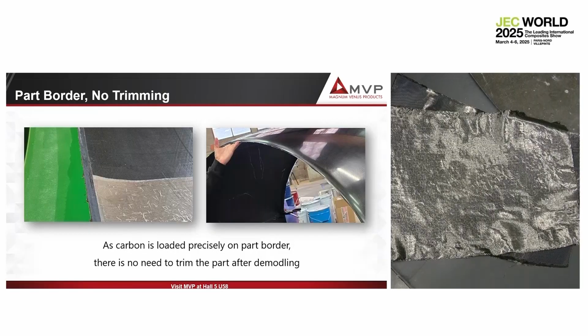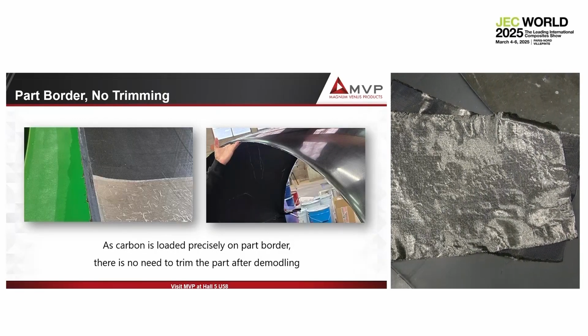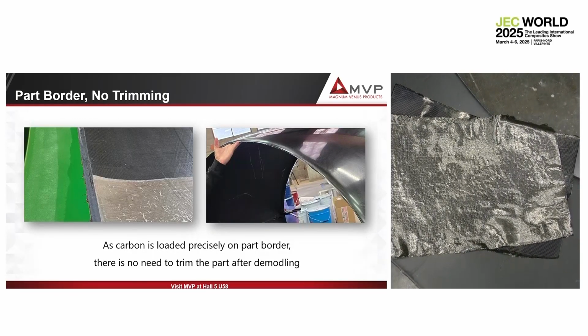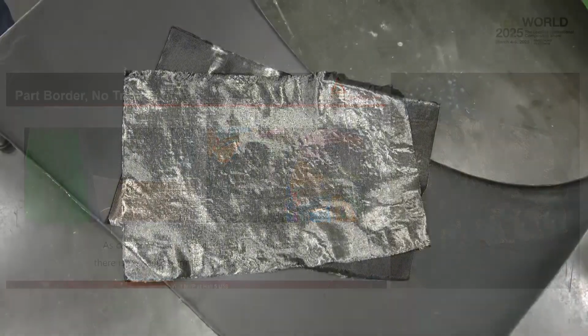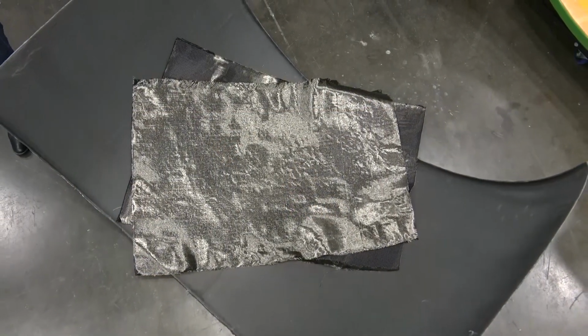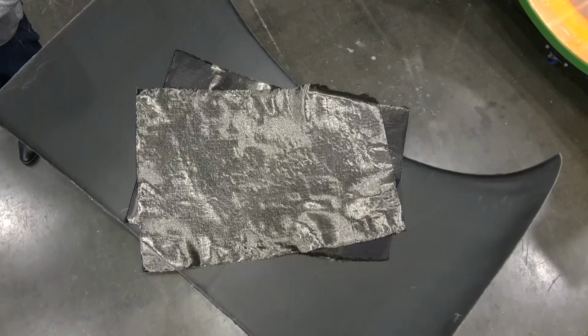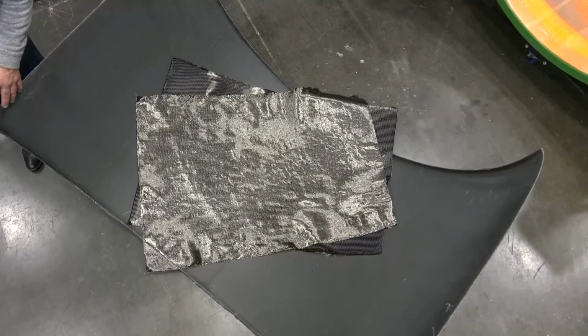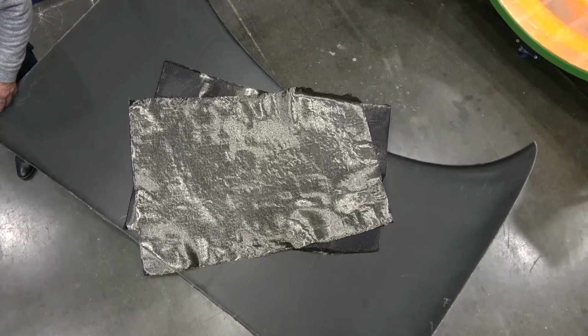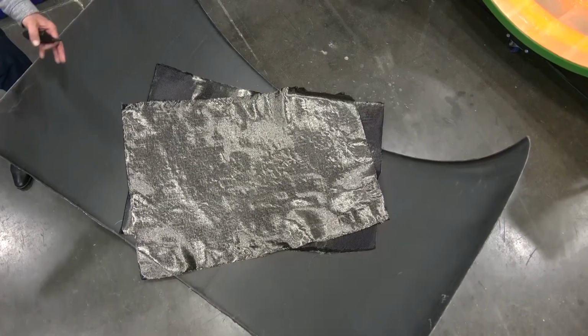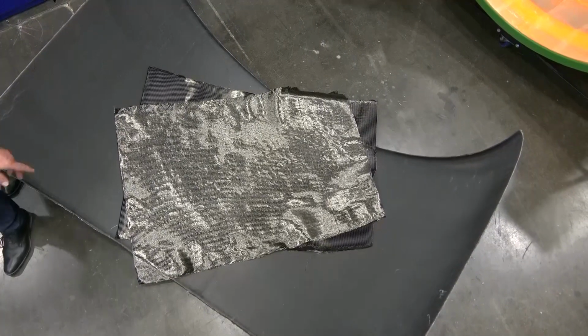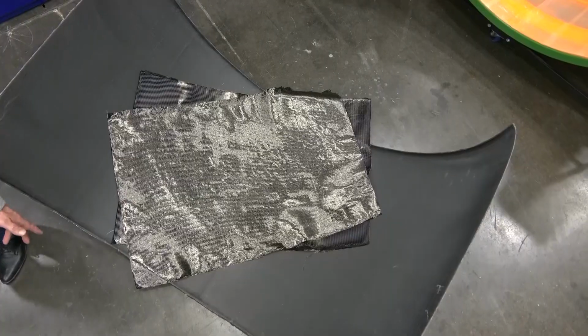Another thing, as you can see on the part, we take the time to load the carbon precisely. So for that, when we design the mold, we make a mark or a step on the part border. So instead of trimming the part, we take the time to load the fiber in the right position. Like that, when we demold, there is nothing to do. So it's better to use time to load properly than to trim the part after. That creates a lot of dust, especially with carbon.